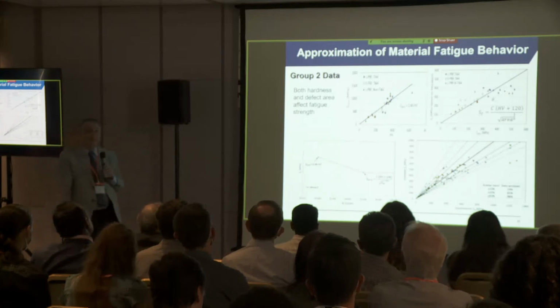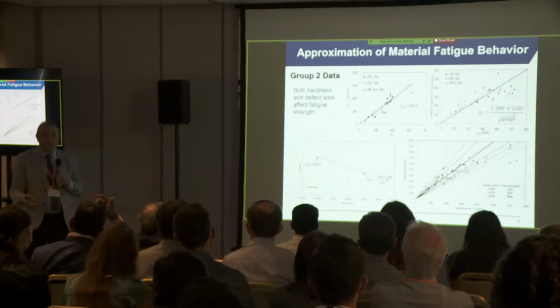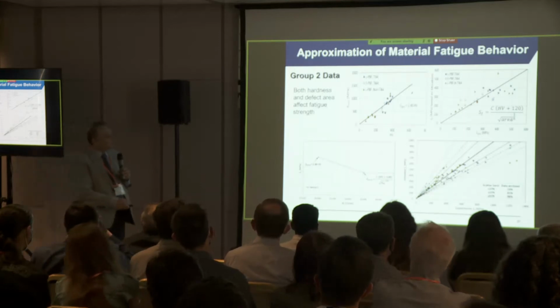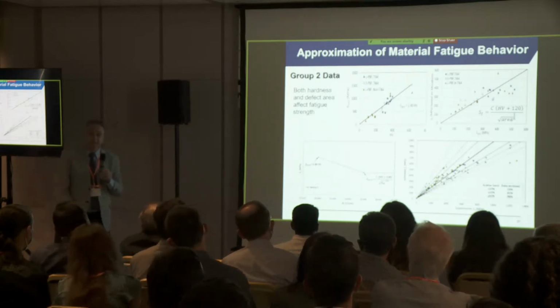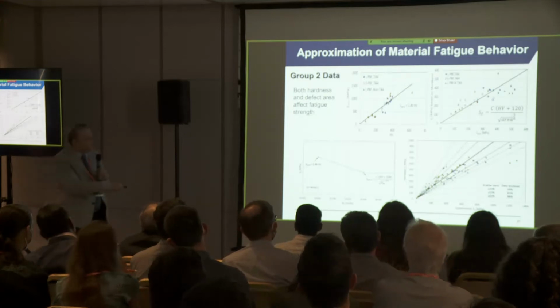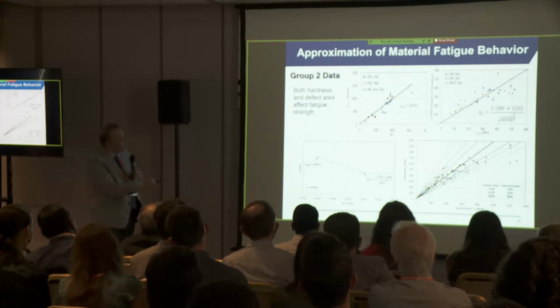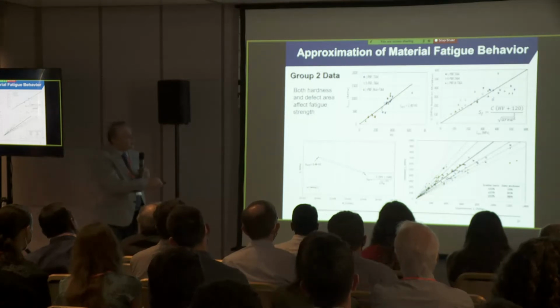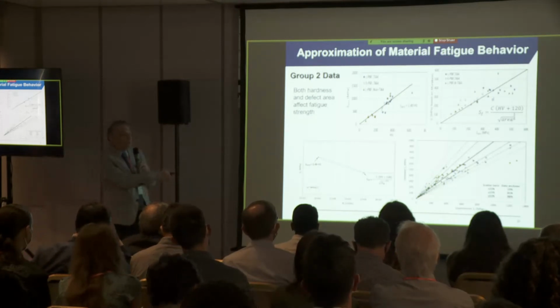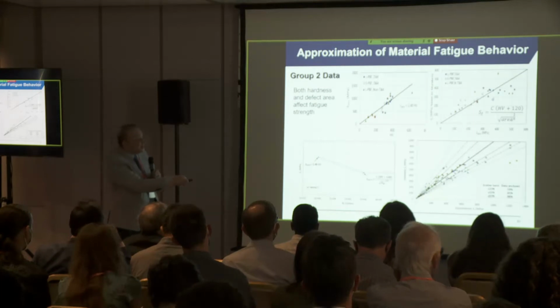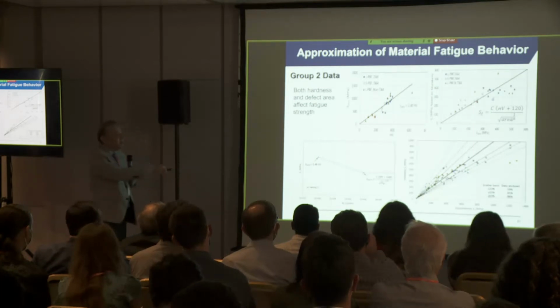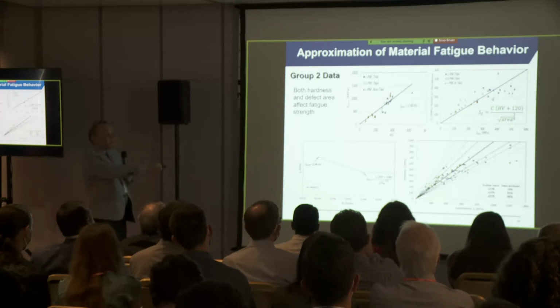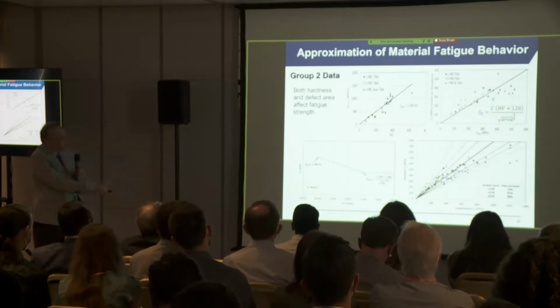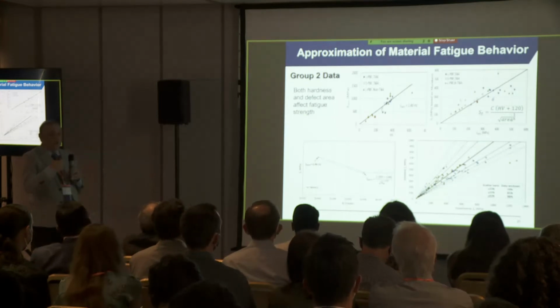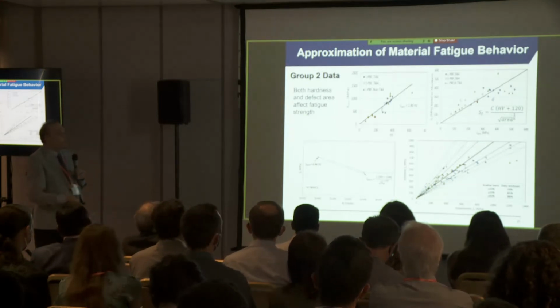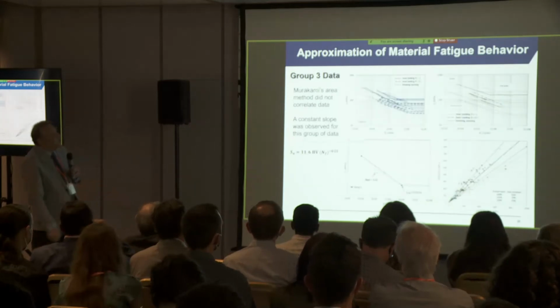For group 2 data, because defects play a key role, they have to be taken into account. So we use Murakami's method for dealing with defects. And when you do that, again, there is good correlation between fatigue strength at 1,000 cycles and hardness, and then between fatigue strength at 1,000,000 cycles and fatigue strength that you get from hardness and area of the defect. So that has to be taken into account. Again, not bad predictions for only relying on hardness and defect area. And then the third group of data is most challenging.